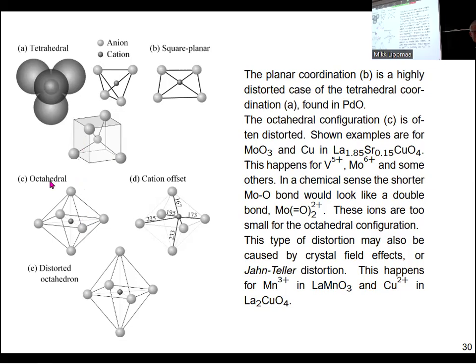The most common bonding type is this one, which is the octahedral case. So you have 6 oxygens around the metal site. And we will look at a number of details of these types of systems, because there are very, very important distortions in some of these. So for example, when you go to ferroelectric or piezoelectric materials, we often have metal offsets from the center of the octahedron. So some bonds become significantly shorter